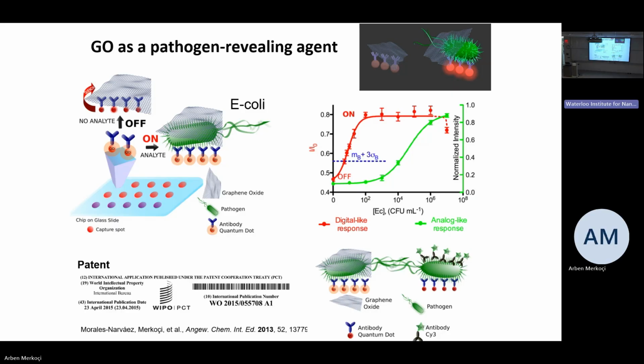And here you see the sample that contains bacteria. You see the quantum dots connected with antibodies are recognizing, interacting with these bacteria. And due to some electrostatic forces, the graphene oxide flakes are interacting with bacteria also on the surface of these bacteria. So the distance between the graphene oxide and the quantum dots is rather large, because bacteria are around 2-3 micrometers in size. But in the case of the sample that does not contain bacteria, the graphene oxide are almost approaching the quantum dot. So the sample that contains bacteria has the fluorescence on, and it turns off when the sample does not contain bacteria.